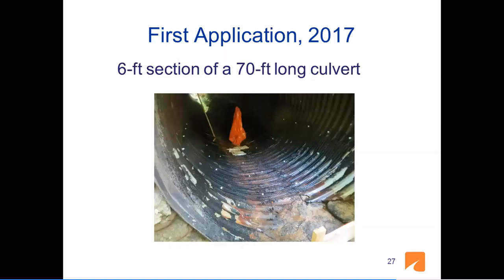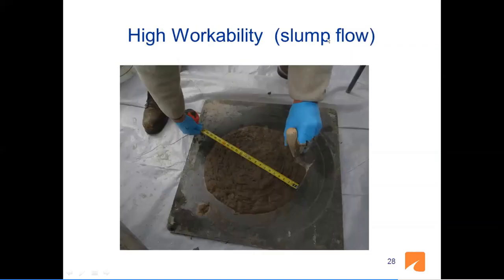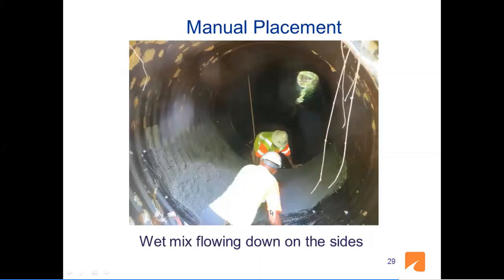Then we said, okay, let's do a small section, 6-foot section, and see how it will, with this geogrid, stay in that culvert, at the bottom of the culvert. And as you see, there are also corrugations there that help us to keep the material in there. So we again made a highly workable ECC material, as you see here, pretty high, it's a self-consolidating material. And we manually placed this material. But it was a wet mix, as you see, it's a self-consolidating mix. Wet mix meaning the high slump flow in this, rather than slump, a slump flow measurement,